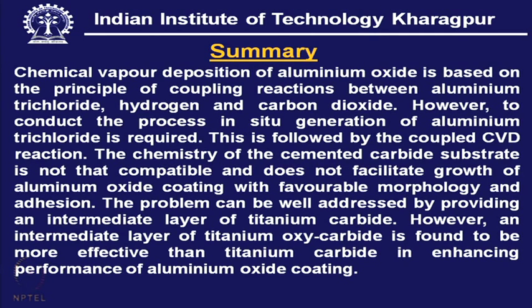Chemical vapor deposition of aluminium oxide is based on the principle of coupling reactions between aluminium trichloride, hydrogen and carbon dioxide. However, to conduct the process, in situ generation of aluminium trichloride is required. This is followed by the coupled CVD reaction. The chemistry of the cemented carbide substrate is not that compatible and does not facilitate growth of aluminium oxide coating with favorable morphology and adhesion. The problem can be well addressed by providing an intermediate layer of titanium carbide. However, an intermediate layer of titanium oxycarbide is found to be more effective than titanium carbide in enhancing the performance of aluminium oxide coating.